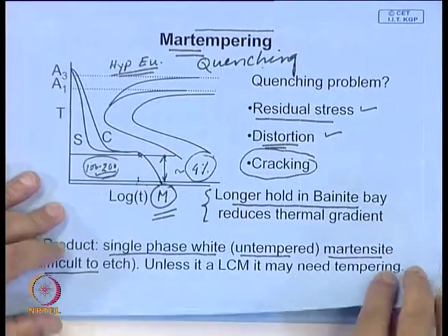But if the carbon content is high, there is a possibility that there will be some retained austenite left in the material, and so the structure will be unstable, dimensionally unstable. It may transform during service, which may lead to change in dimensions. So, particularly in rather high carbon steels, it will be advisable after martempering that some amount of tempering may be necessary.